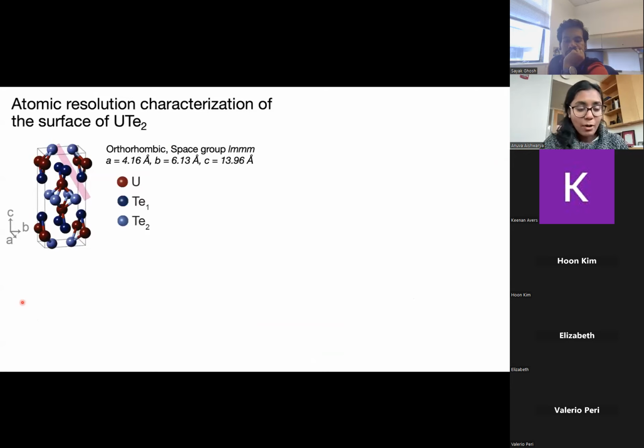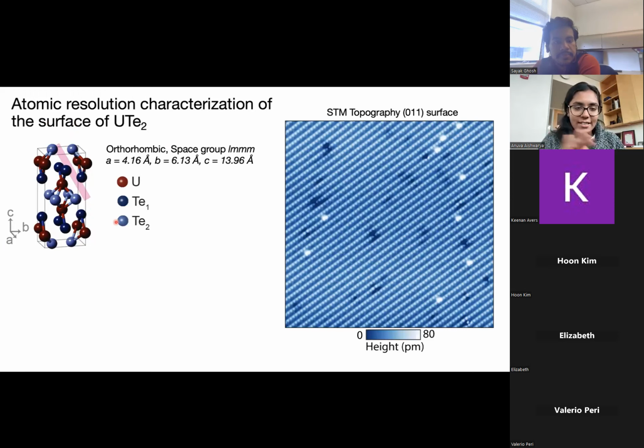UTe2 has this body-centered orthorhombic crystal structure where there are two different kinds of tellurium. They're different because the bond length between the U and Te is slightly different for two of these atoms. The uranium forms this two-legged ladder structure that goes along the a direction. This is the two parts of the ladder. And then when we try to cleave it in STM, it cleaves along this strange plane, which is shown by this pink rectangle. This is the (0 1 1) facet, and that reveals these big, beautiful terraces of (0 1 1).